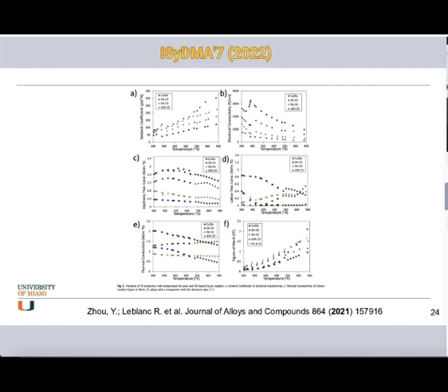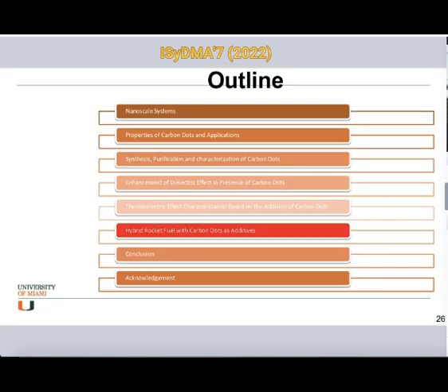It was concluded also that the presence of the carbon dots promotes the energy filtering effect, which ensures a high Seebeck coefficient and low thermal conductivity. So that was important if we want to improve this thermoelectric effect: to use the carbon dots at a very low percentage.